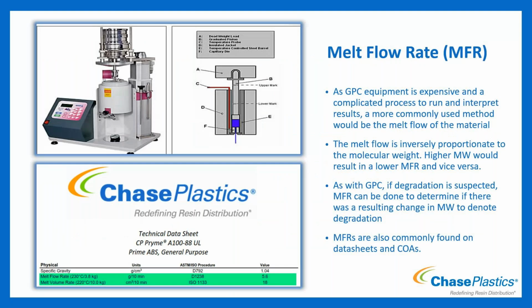On the flip side, the more common way to do it, only because GPC is quite expensive and a very complicated process. It's also kind of complicated to try to interpret the results. And so you'd have to have someone that's quite trained to be able to do that. A more simple way to do it would be to do a melt flow rate comparison. So in the materials where you can use melt flow rate, there are some that it is difficult to do that with, stuff like your nylon or your polyesters, because they're heavily influenced by moisture. We would not use necessarily a melt flow rate for it.